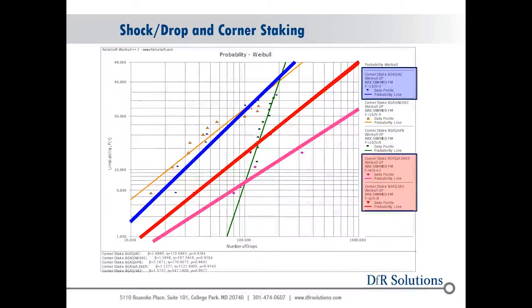When we go to a larger volume of staking, these are those 3 coupons I showed. We have our tin lead, which is the green line. We have some lead-free, SAC 305, SN100, and then we have 2 different corner stakes, a UA 2605 and a 1583. So yes, there's a function of the corner staking material. But you can see all these now are very close.